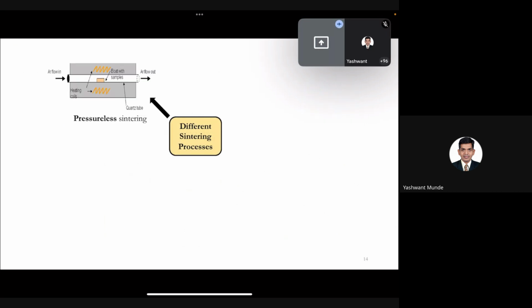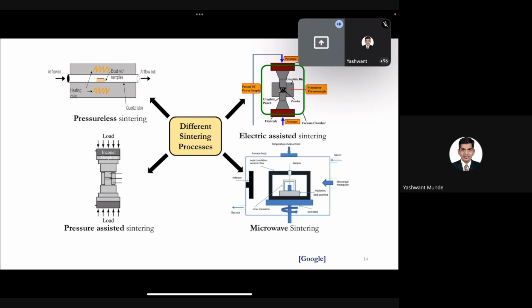So we can use different types of sintering processes. There is pressureless sintering, where you have a conventional tube furnace and you just put your sample there and heat it up. There is no pressure on your sample. There is pressure assisted sintering, when you are putting pressure on the sample. And there is electrical assisted sintering, when you are putting pressure and giving a potential from a DC power supply, which gives very fast heating and large temperature at certain concentrated points. And there is microwave sintering, when you have a microwave magnetron generating microwave energy, which is absorbed by the sample and heats it from the center. The heat goes from center to outside. Here the heat goes from outside to inside.